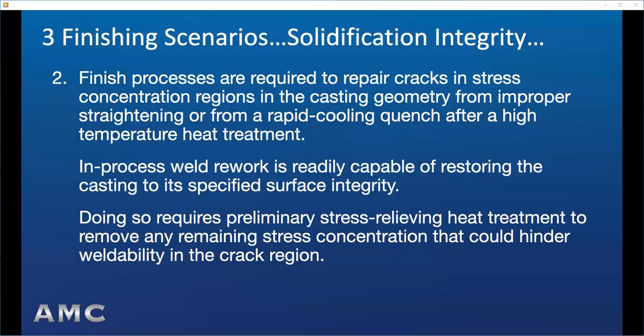Second, finishing processes are required to repair cracks in stress concentration regions in the casting geometry from improper straightening or from a rapid cooling quench after a high temperature heat treatment. The in-process weld rework process that Mike described in his segment is readily capable of restoring the casting to its specified surface integrity. To do so with certainty requires a preliminary stress relieving heat treatment to remove any remaining stress concentration that could hinder the weldability of the crack region.